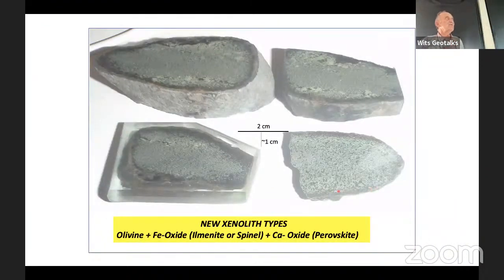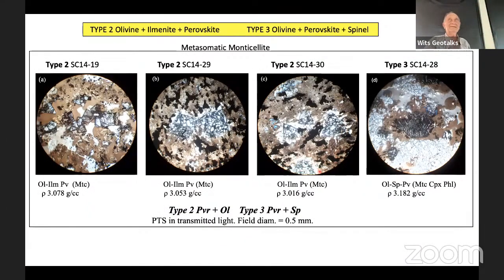So here are the four samples from Liberia. I've referred to these as type one, the ilmenite clinopyroxene intergrowth, and as you see from the scale, they're not very big. So these are in polished mounts. And the green material here is olivine, and the darker spots are either ilmenite in three of them, and in this one is spinel. So we have a close association then, an oxide plus a silicate, number one. Secondly, an oxide plus a silicate of diverse both compositions and crystal structure. So that was the first attraction in the field, as you saw the difference.